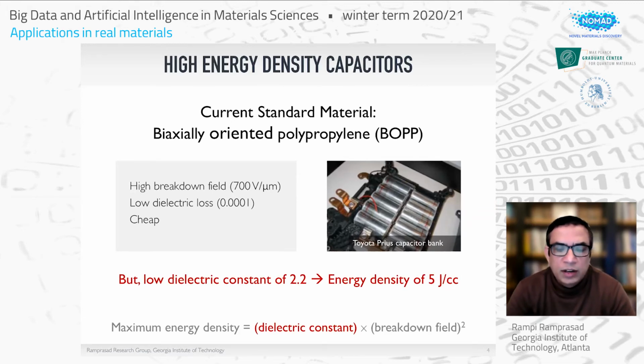The problem is that this material has a very low dielectric constant of about 2.2. This translates to an energy density of about 5 joules per cc for this material, right? This is the maximum electrostatic energy you can store in this material per volume, right? 5 joules per cc. This is an important number. Let's keep this number in mind, because whenever you want to design a new material that is better than this, you want to make sure that that material has a higher energy density than this standard material, right? So this is the figure of merit that we are going to keep in mind.